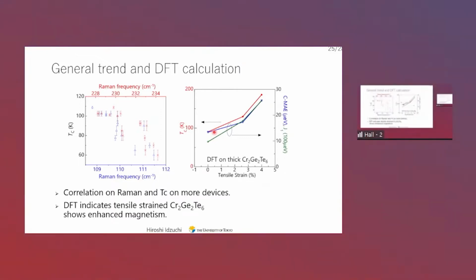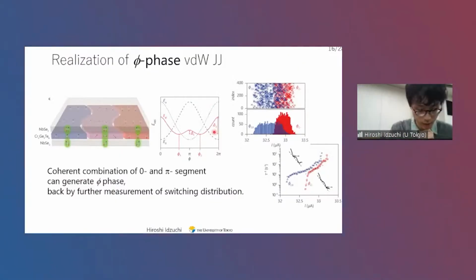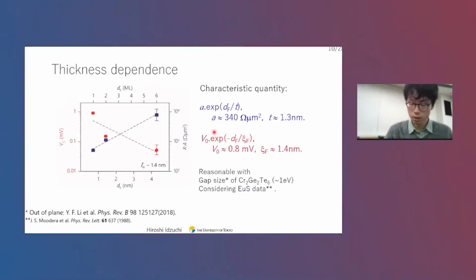You have shown some supercurrent images. How did you compare the supercurrent with other 2D systems that have been used in Josephson junctions? I myself do not, but back in these days there were colleagues using, for instance, graphene and hBN for the barrier, so we have had some discussion. And how does it compare with those values? For the monolayer case, for CrGeTe3 it was rather high. It was comparable to a niobium diselenide graphene niobium diselenide device.